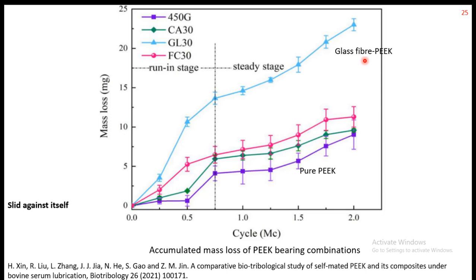Although the previous result I showed you had cases of failure for 2 patients, the conclusion was that it was because of the poor bonding between the fiber and the matrix. So perhaps carbon fiber has got some promise here. Glass fiber did not show very encouraging results. So this is the case of polymer sliding against polymer.